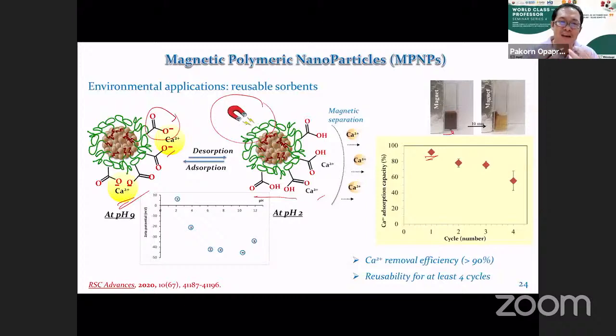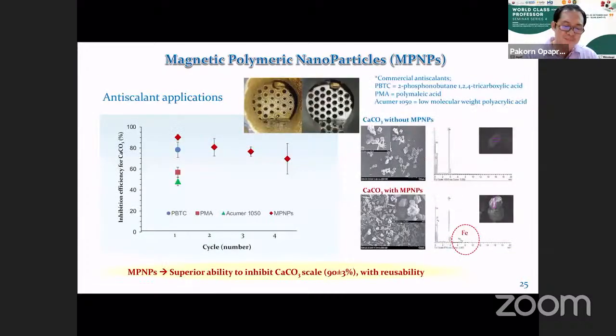After collecting them, we can regenerate this material by using an acid solution, and then we can reapply it. We can reapply it in at least 4 cycles. We can see that the adsorbent capacity doesn't change much during the first 3 or 4 cycles. So this can be used as a reusable adsorbent in environmental applications.